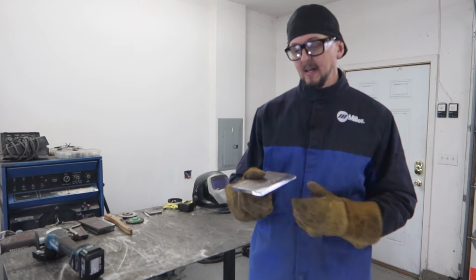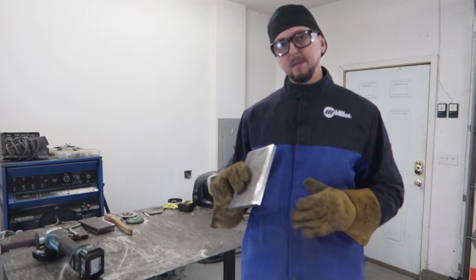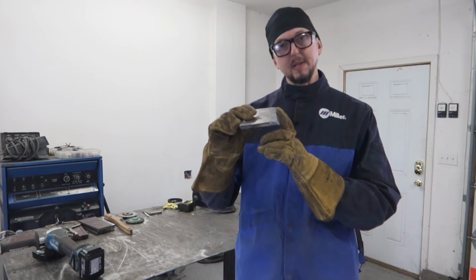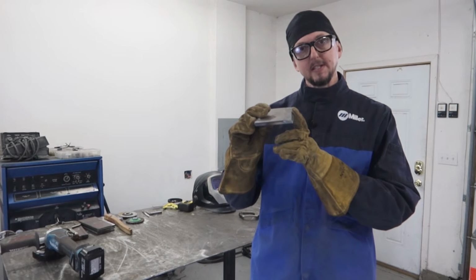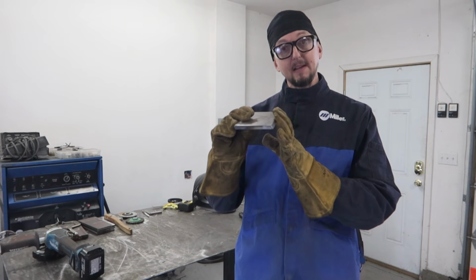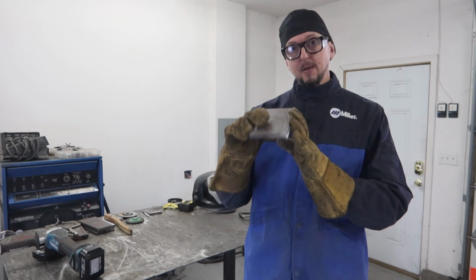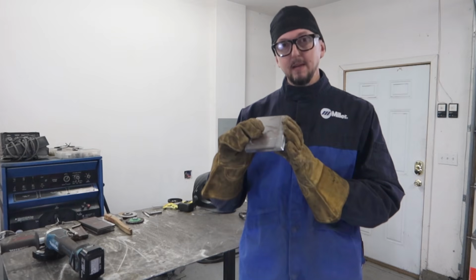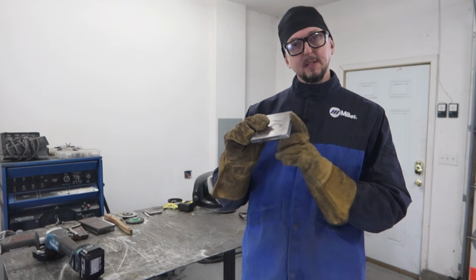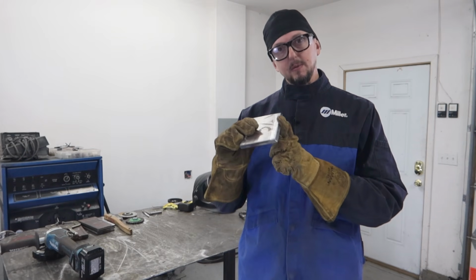But for this weld, basically you can leave it a knife edge, but then your parameters will have to be turned down, because if you leave it a knife edge on an open root, it's not going to take very much current to melt that away very quickly. So what I typically do is I put about a 30 thousandths root face on there.